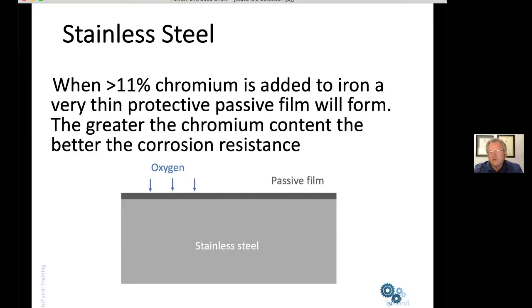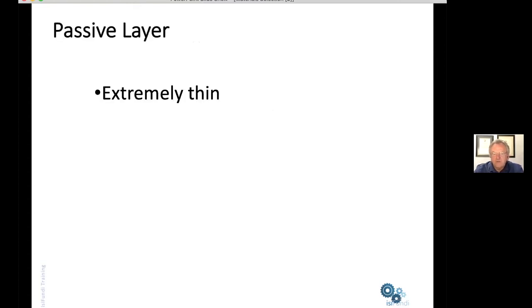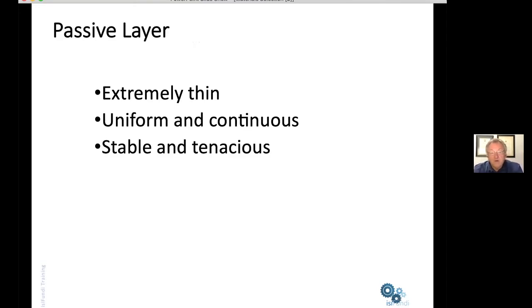Everybody has heard about nanotechnology. Well, that passive film is about 3.5 nanometers thick. That's all. And it provides the skin that then prevents the material from corroding. If you starve a stainless steel of oxygen, you can end up with some unintended consequences. So this passive layer, as we've seen, is extremely thin, uniform, continuous, and stable. In other words, it doesn't change with changing conditions, except in the absence of oxygen.